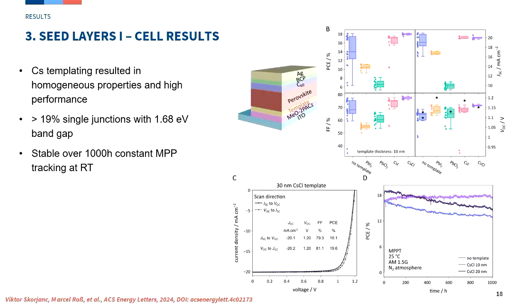If you do everything right, you can also get a stable output, 1,000-hour tracking at room temperature, and we also have very nice data at 90 degrees for accelerated lifetime testing. We're very confident that co-evaporation has a very good benefit in terms of stability of the perovskite.